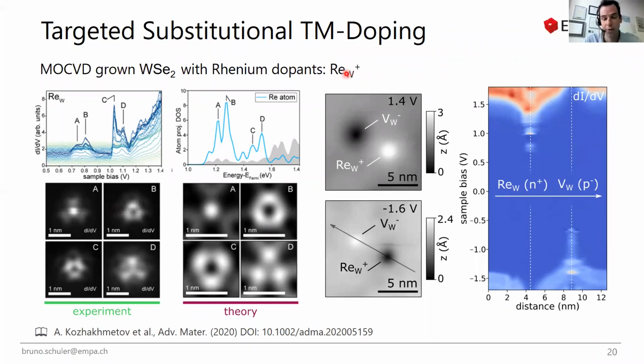Because rhenium has essentially nominally one electron more, it is expected to be an n-type dopant, and it's also what we see. We see it has states close to the conduction band, and in this case it's actually positive, so it's ionized, because this state is getting depleted as the electron can simply leave to the graphene substrate. So we see n-type dopants which are positively charged, and we see p-type dopants which are negatively charged. I think that's also something cool to play around with.